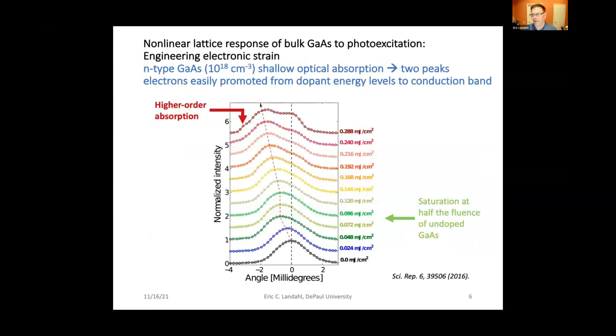Here's an example of how you can then use that to engineer the strain in the material. So this is an identical experiment to what I just showed, but using doped N-type gallium arsenide. So this is tellurium doped to 10 to the 18 per cubic centimeter, again, a bulk crystal at room temperature. It, of course, exhibits a much shallower optical absorption, about 100 nanometers thick. And the result of that is you see multiple peaks when you start to have significant lattice shift.